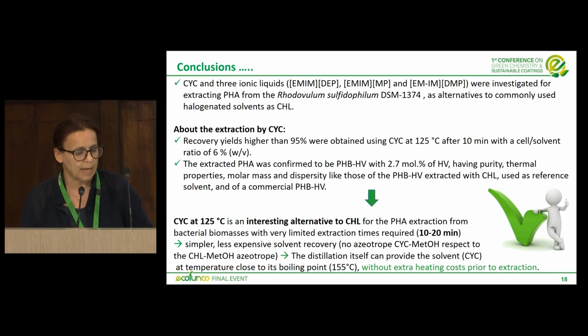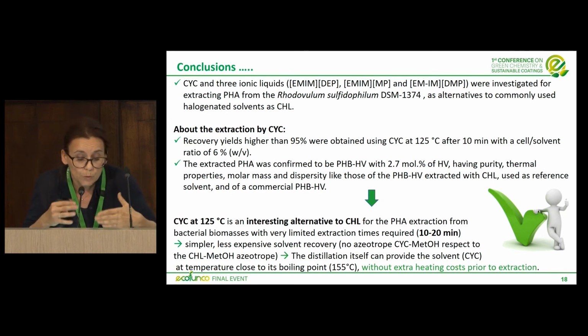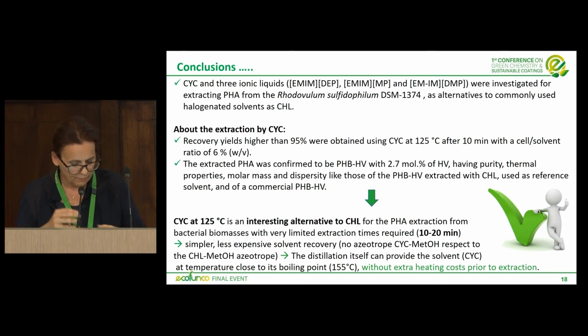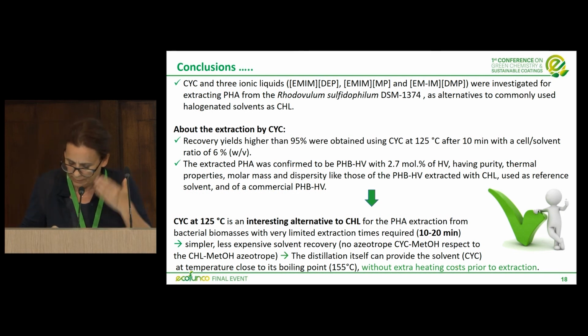after the precipitation step of the PHA, because the cyclohexanone and methanol don't form any azeotrope. On the contrary, the chloroform and methanol form an azeotrope, and consequently, the distillation, the typical process used to recover these solvents on the industrial scale, is more expensive in the case of the chloroform with respect to the cyclohexanone. In addition, the distillation itself can provide the solvent at a temperature close to its boiling point, 155 degrees, without extra heating cost prior to the extraction, and this is good in terms of cost.